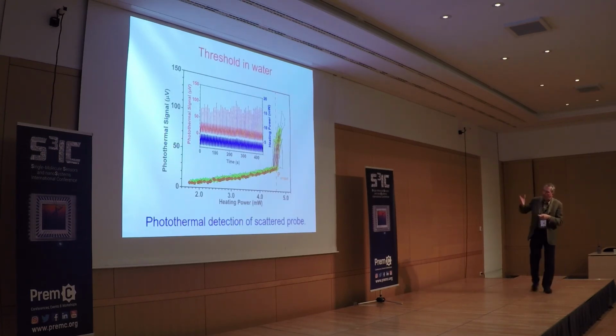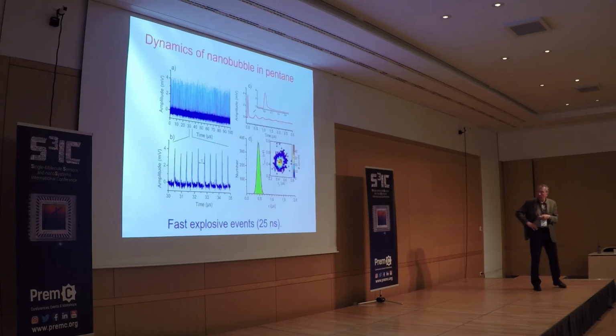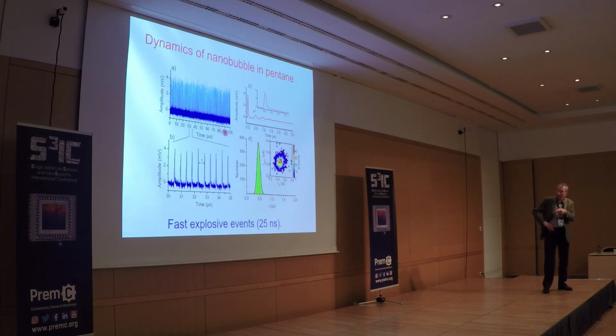So if we do this experiment in photothermal, you see something sudden happening here. This is this boiling transition, as we expect. But actually, when we looked at the time trace, what you see is this. The time trace, while we're heating continuously, is very noisy. This time trace is shown here, on a scale of 100 microseconds. If you zoom in, you see that there is a burst, an explosion actually, every microsecond or half a microsecond. So very high rate bursts, which are caused by instabilities.